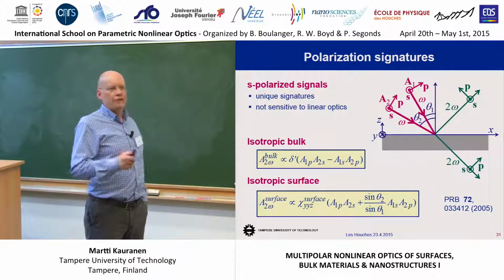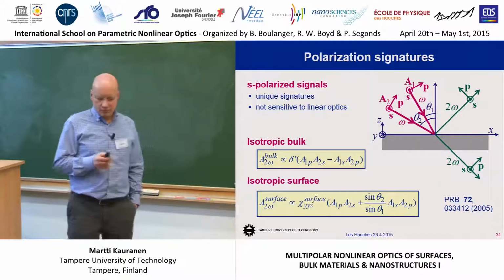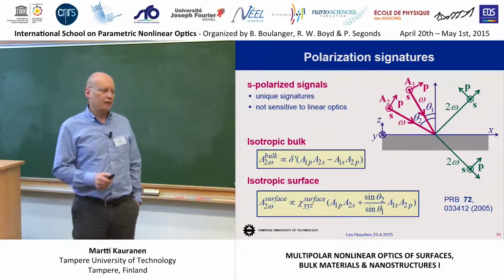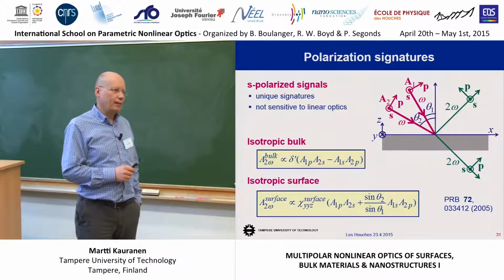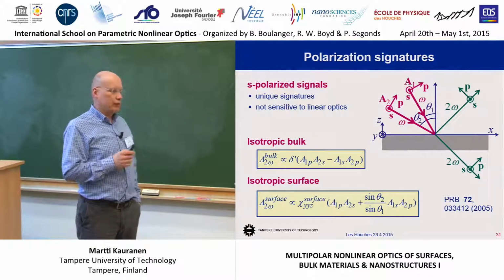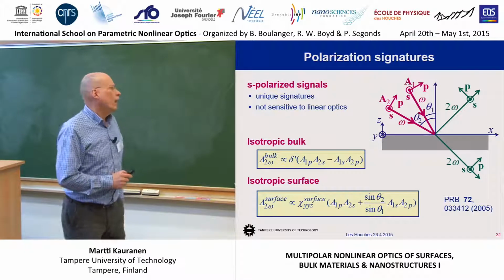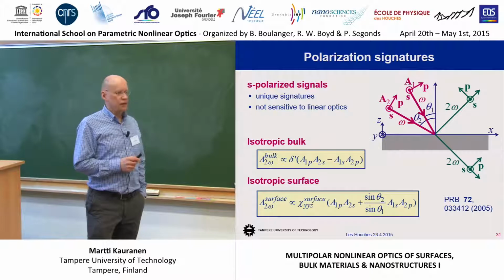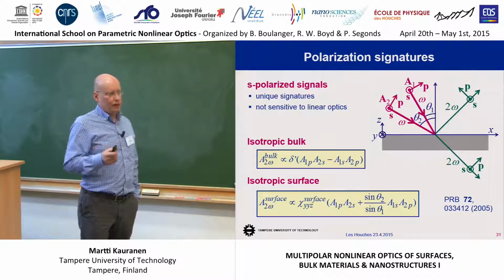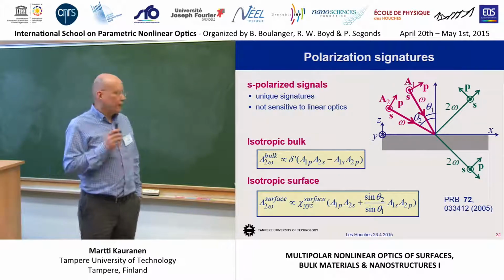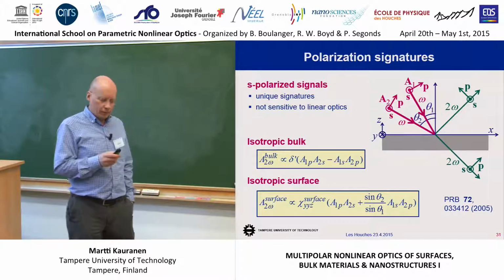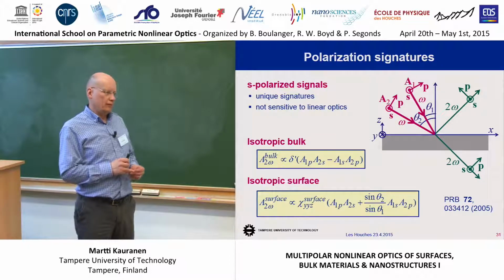We got some of the first data for some of the samples, and we could not fit the data with any reasonable electric-dipole surface model. And we started looking into what might be going on, and we realized that we are measuring the bulk contribution. And we got this really direct evidence of the bulk contribution by doing polarization measurements.